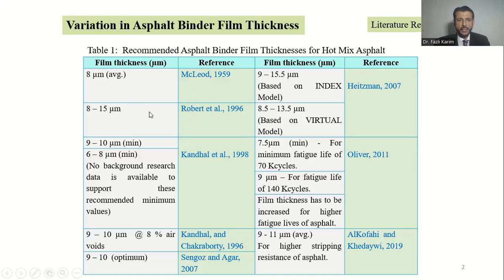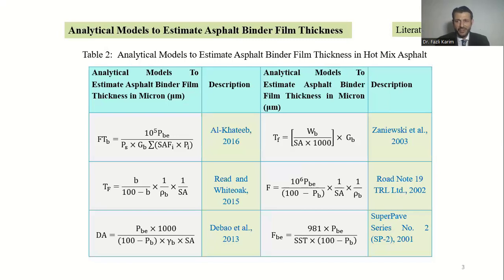But according to Robert, 8 to 15 micrometer. According to Kendall, 9 to 10. We also have 6 to 8 micron, but no background research data is available to support these values. And similarly, according to Heitzman, 9 to 15.5 and Oliver, 7.5 micrometer. So while looking at this table, it's a bit confusing. Or we can say there are discrepancies in these values. Now the question is: where do these values come from? So these values have been assessed using analytical models.